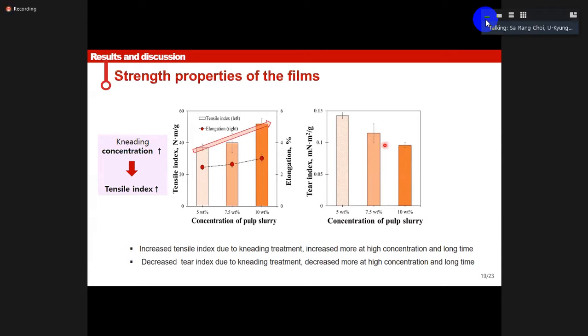Next, look at the tear index graph on the right. Contrary to the tensile index, the tear index gradually decreased as the pulp concentration increased. The kneaded sample, which had the best micronization effect, showed the highest tensile index and the lowest tear index. This is because the hydroxyl groups of the fiber increased due to micronization and hydrogen bonding was improved, which increased the tensile index, tensile strength.